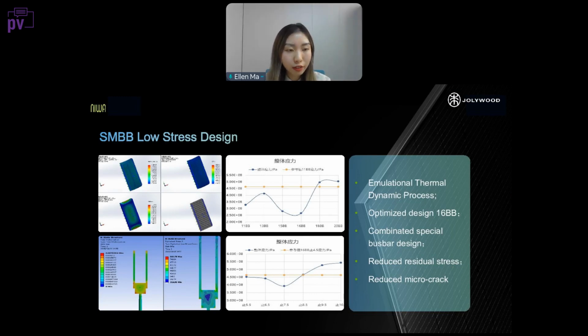And also, our NIWA products have adopted SMBB technologies, which is a low-stress design. We did a simulation of the thermodynamic process, and we found that the 16 busbar is the best design for the modules. Combined with the special busbar design, we can significantly reduce the residual stress and also reduce micro cracks, to ensure long-term reliability for our customers.